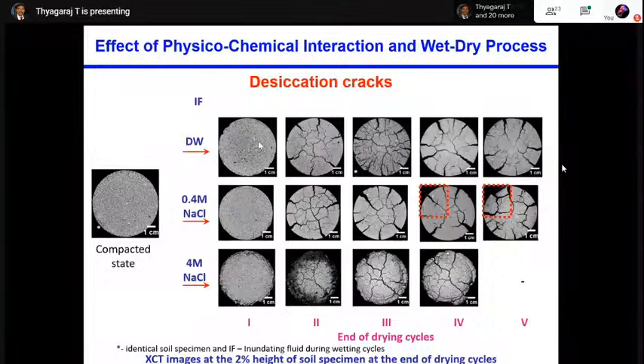You can see that in the distilled water sample a lot of cracks are there, and even with the 0.4 molar solution cracks developed. But in the 4 molar solution sample, you can see that the structure is porous and the cracks are appearing at the same place. That is the case for 0.4 molar also. It occurred at the same place after the fifth drying cycle.